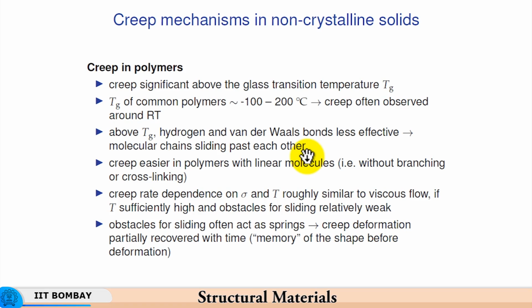Under room temperature conditions or low temperature conditions, these secondary forces or secondary bonds are quite strong, and therefore the sliding of the chains relative to each other is hard, because in polymers you have macromolecules which are folded over each other, and so these molecular chains have to slide so as to deform. Now, if the ease of sliding increases by weakening of these hydrogen and van der Waals forces, then they can slide past each other, and creep becomes easier in polymers with linear molecules without cross branching or without intertwining with respect to each other, because this interlocking can increase the creep resistance.